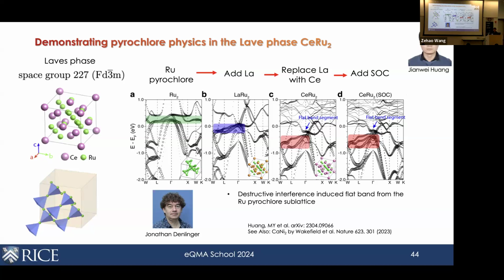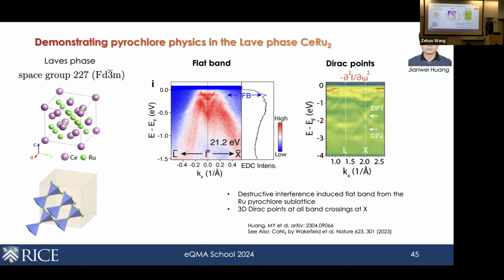Experimentally, this is the work by my postdoc Jianwei Huang here. He did ARPES on this cubic system, and what he finds is that you can see this portion of the flat band at the energy associated with the helium lamp, and we know that at this energy you cannot have any cross-section contribution from the f electron. So this definitely comes from the ruthenium d states. That's the flat band originating from the pyrochlore lattice. Secondly, we can also see that at the X point there are these Dirac crossings, which are associated with the non-symmorphic symmetry in these compounds. So in this system, we can identify the two key signatures associated with the three-dimensional pyrochlore lattice.